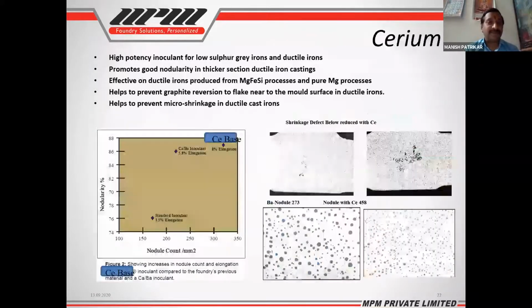Cerium. So cerium we are again using as a highly potent inoculant. Cerium, like strontium for gray iron, is supposed to give better inoculation. Cerium or RE based inoculants are supposed to be better for SG iron because they are actually used to reduce the shrinkage defect. It's just like the strontium effect in gray iron. For SG iron, cerium does the same thing and also helps to reduce the tramp elements.